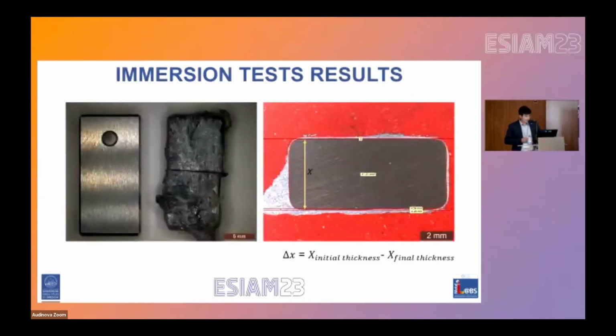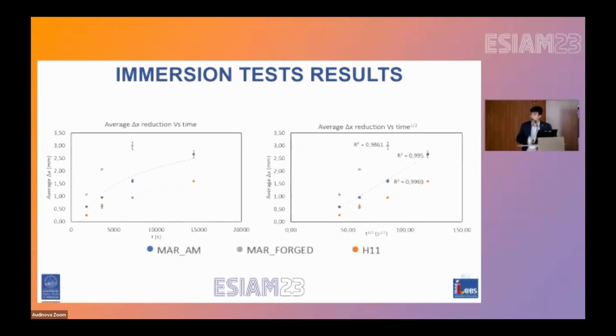Here you can see an example of the sample surface before and after the 1 hour of immersion test. The parameter chosen to evaluate the corrosion resistance was the thickness loss. So before the immersion, each sample was measured by a caliper, and at the end of the test, the final thickness was measured in the cross-section of each sample using a digital microscope.